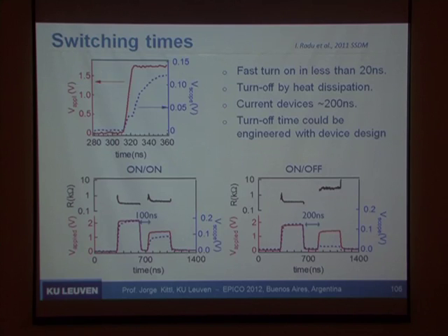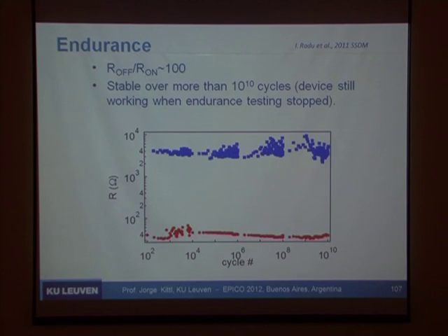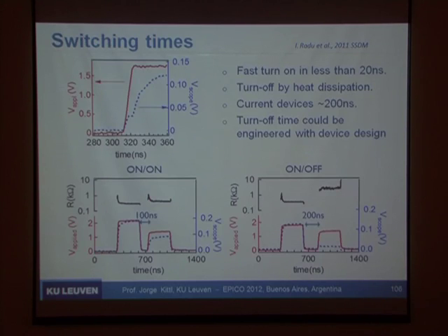And we try to make a point. So these are some examples of switching where we can show basically 100 nanoseconds. But again, we're far from the limit. If you just calculate after nucleation how the transformation propagates, it's extremely fast. Somewhere in between will be the real switching time of a device. We're not sure, but it will be in a few nanoseconds,